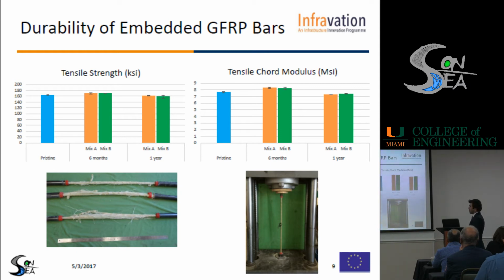So the test is also continuing. So after a year, we went there again. We extracted more bars, and again, as you can see, after a year, still they are the same. So after a year into the accelerated conditioning, you're getting almost the same tensile strength. And also the chord modulus, you can see, is still comparable.